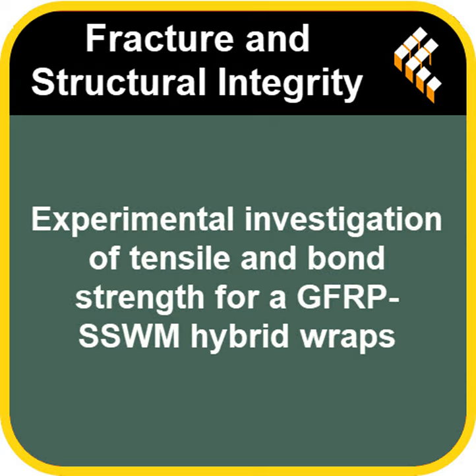Okay, and the hybrids, where did they land? This is the really compelling part. The hybrid specimens, particularly that GS configuration with the Sikadur 30 LP adhesive, achieved almost 90% capacity utilization. Wow, so almost as good as the pure SSWM bond, but with the added strength of GFRP. Exactly. It shows superior bonding efficiency and effective load transfer between the concrete, the mesh, the GFRP, and the epoxy. It means that hybrid system, with the right glue, gets much, much closer to actually delivering its full theoretical strength in practice. That seems like a massive win, getting the strength and making sure it actually works when attached to the structure. It's a critical finding.